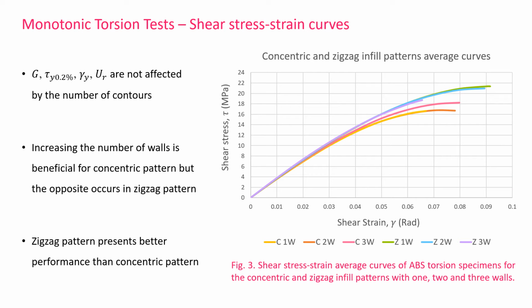Experimental results. From the shear stress-strain curves displayed in Figure 3, it was concluded that shear modulus, shear yield strength, shear yield strain, and resilience modulus are practically not affected by the number of contours in both infill patterns.